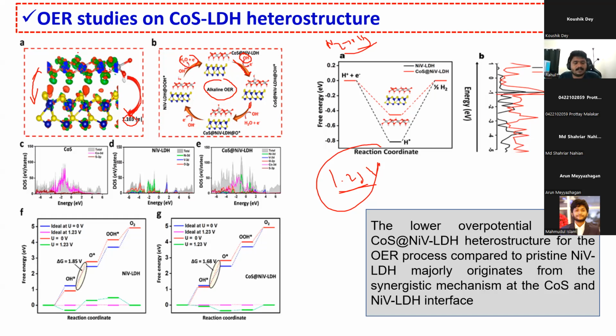So as I told previously, we made a heterostructure with the nickel vanadium LDH and cobalt sulfide. We actually calculated the DOS for the cobalt sulfide. We found that in the Fermi level we have states, so it's conductive in nature. Then we found that even for the nickel vanadium LDH, we have states at the Fermi level, so it's also conductive in nature. When we made the heterostructure, we can also find the states at the Fermi level. So basically, even after the heterostructure formation, our conductivity is retained.